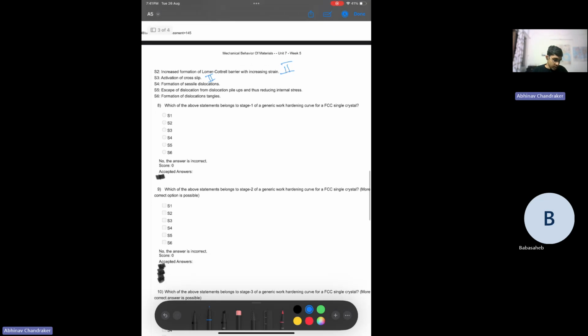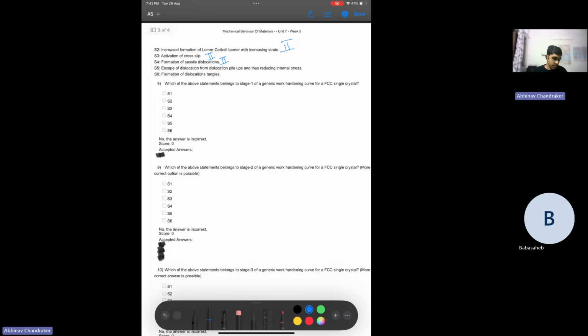It occurs during stage 1, stage 2, and it also takes place in stage 3, but we'll call it stage 2. Formation of sessile dislocations. Sessiles are immobile dislocations. They form in stage 2 itself and act as barriers. Escape of dislocations from dislocation pileups and thus reducing of internal stress. So pileup escape can happen at higher stresses because other slip systems get activated. CRSS of those slip systems gets overcome.